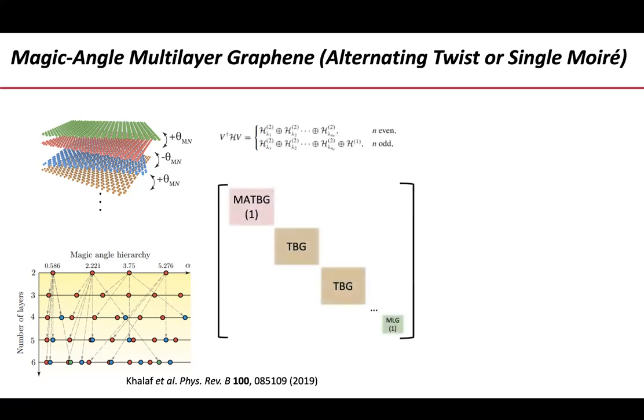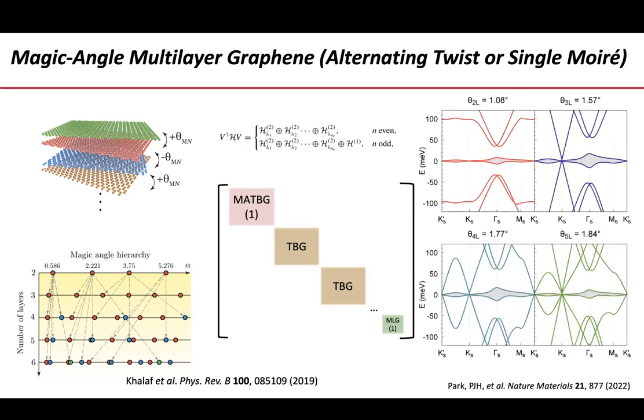Now, the same thing that happens for the trilayer happens for all of these. You can decompose into a change of basis and your Hamiltonian becomes block diagonal, where one block is always a flat band, a magic angle twisted bilayer graphene line, with a renormalized tunneling, which depends on the number of layers. Then you get as many large angle twisted bilayer graphene sectors as extra pairs of layers there are. And if you have a total odd number, you get an extra monolayer graphene. So the electronic structures for 2, 3, 4, 5 layers, and the magic angles are here.